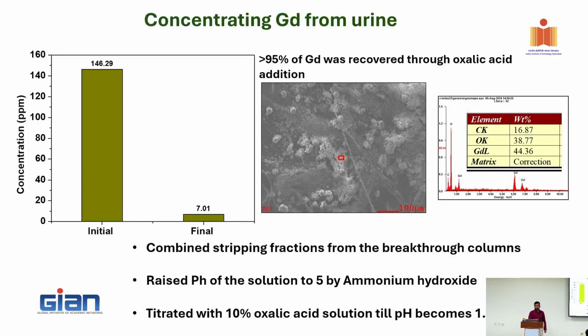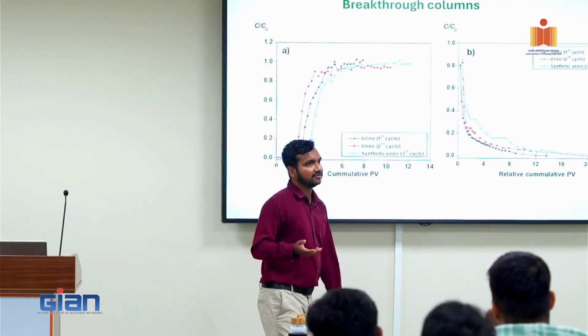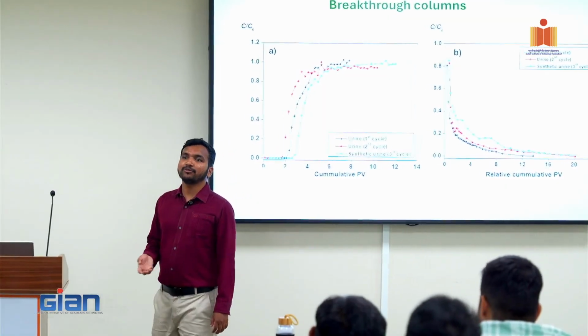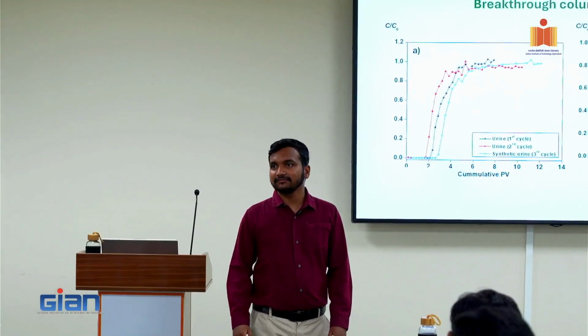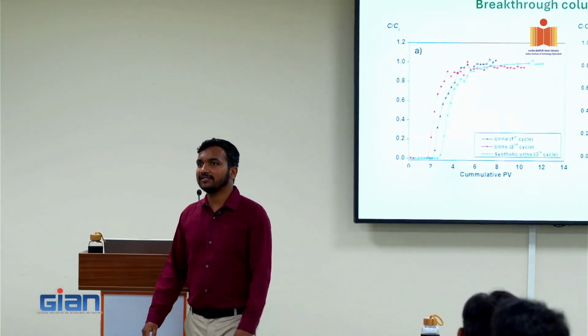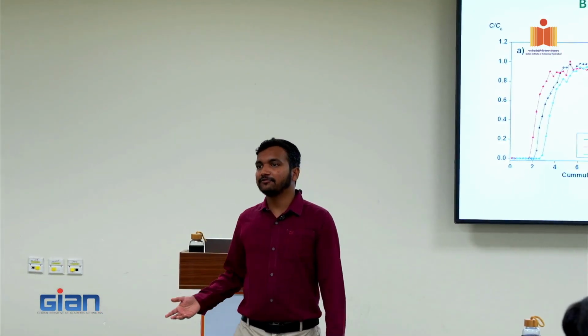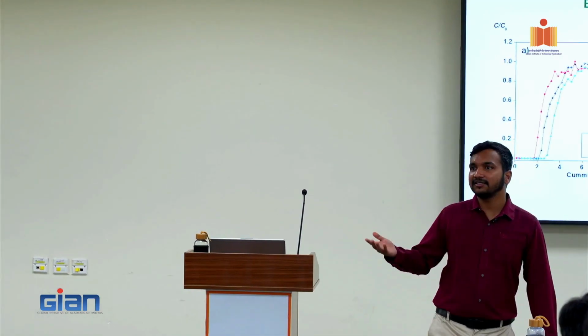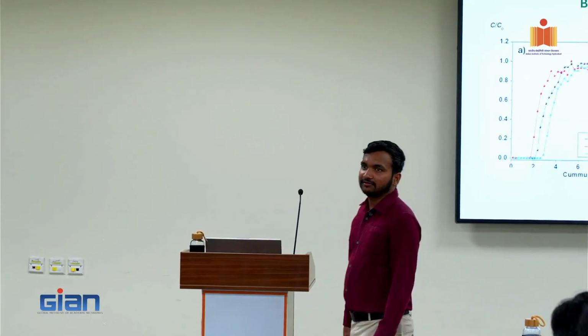So this media we used in laboratory conditions for three cycles. You see, the 3 cycles are giving very similar efficiency and similar trends. We have a loss of less than 5 to 10% reported in the capacities. So at least for 3 cycles, we have proved that it is reusable and recyclable. Yes, of course, we can regenerate, but the regeneration still has to be worked on. We tested only 3 cycles so far because of time considerations.